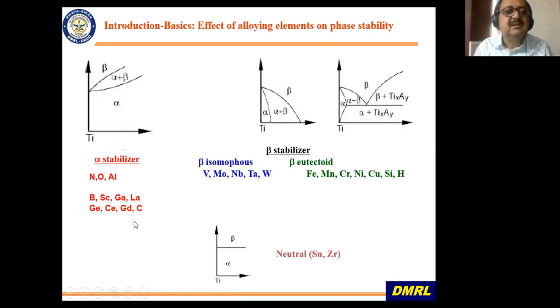What do the alpha stabilizers do? As you can see here, they increase the beta transus temperature and stabilize the alpha phase region. So the alpha phase becomes more stabilized. Now, if we come to beta stabilizers, there are basically two types of beta stabilizers, beta isomorphous and beta eutectoid. The first thing that the beta stabilizer does is reduce the beta transus temperature, both places you can see.